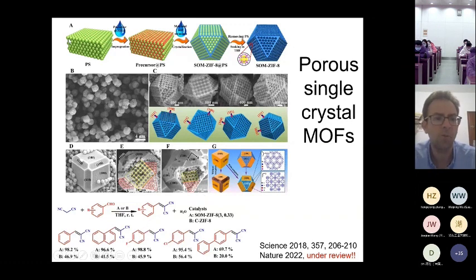This encompassed a very simple approach that you see in the slides, on the utilization of polystyrene beads towards the design of this ZIF-8 type of materials that encompass a unique porosity, including the microporosity that is inherent to the MOF and macroporosity that you nicely see in the slide, generated from the removal of the actual template of the polystyrene beads. In addition, we found this to be single crystalline type of materials that had very useful applications in catalysis.